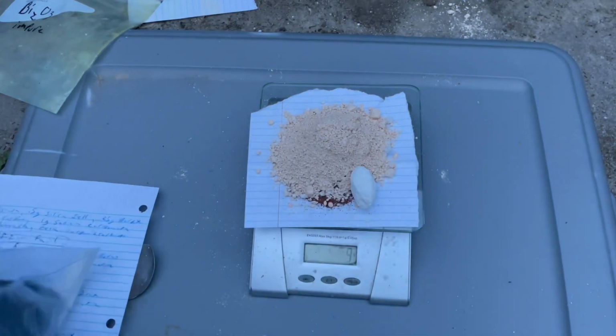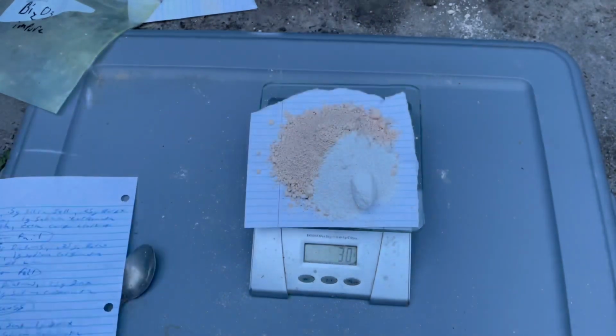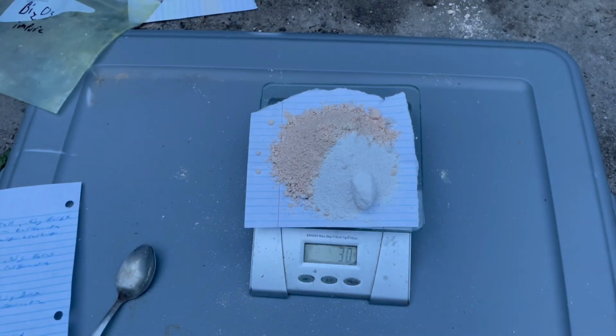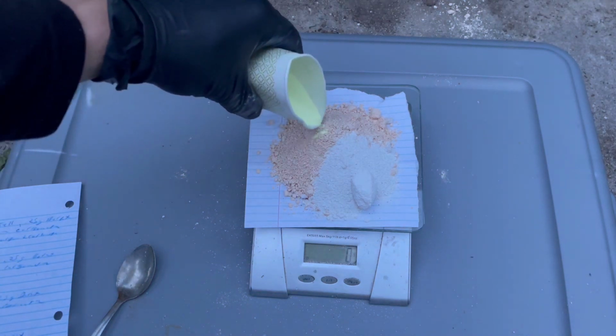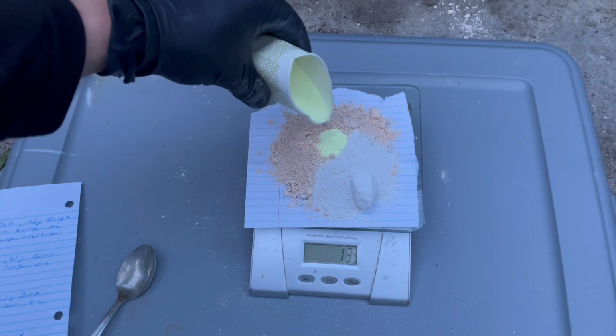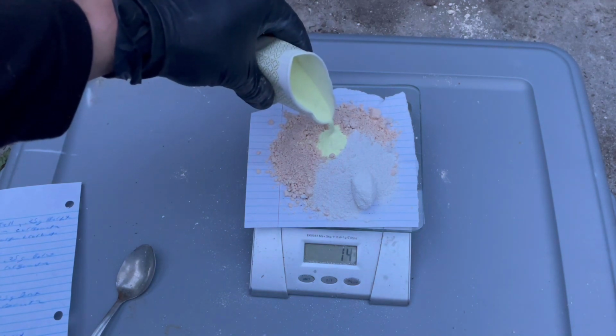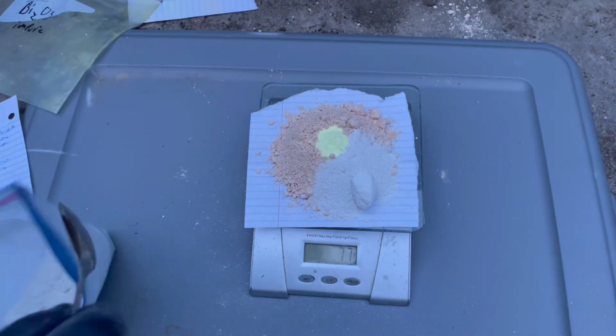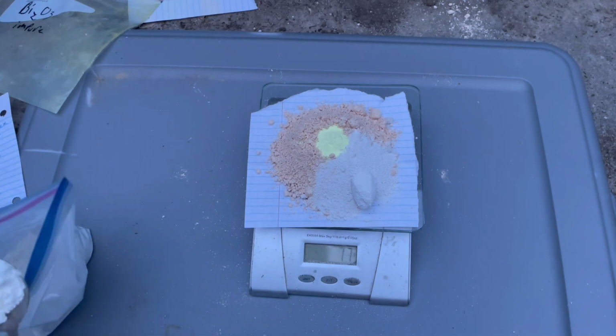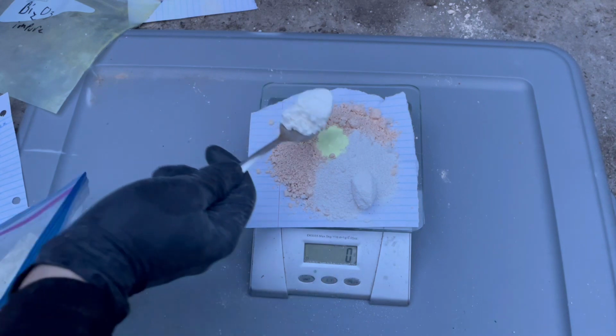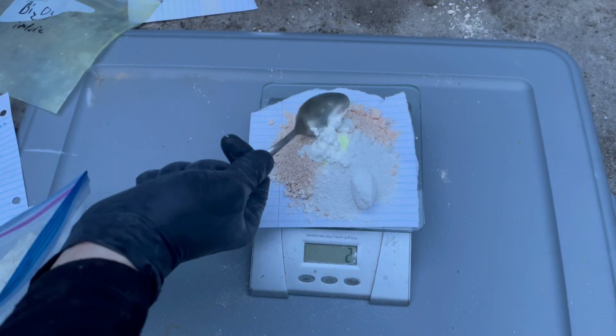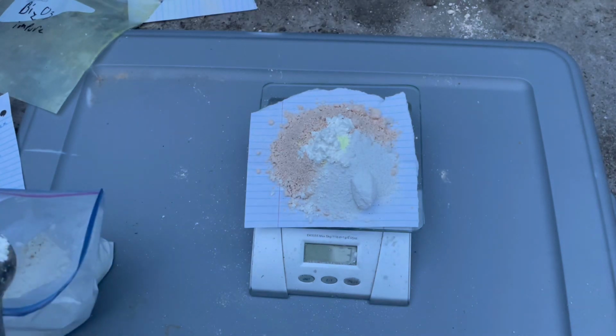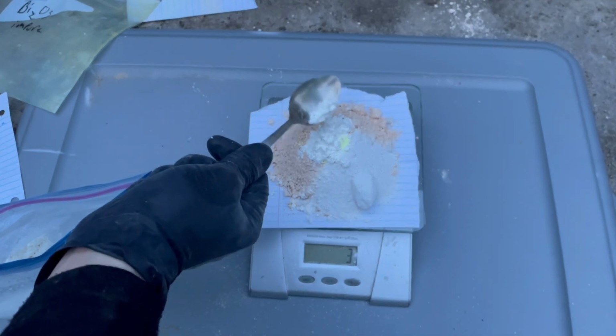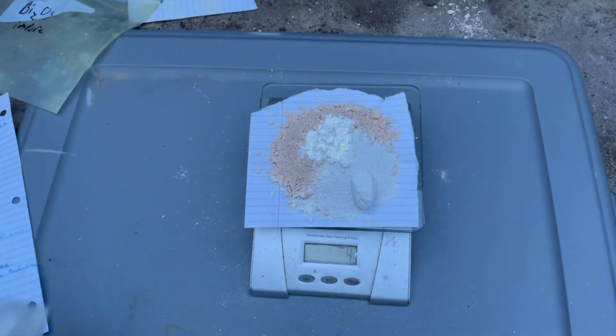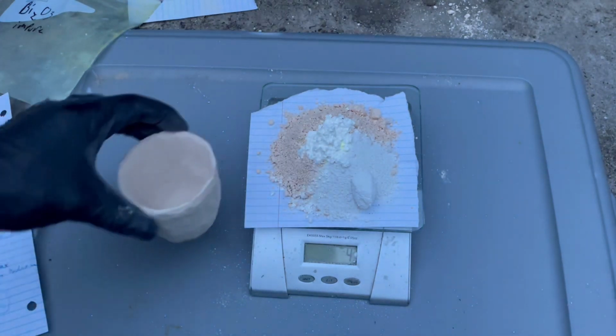30 grams of sodium carbonate. Okay. 16 grams of bismuth oxide, just like before. What was it, 17 grams. Now, for my testing, I discovered that I needed more starch. More than the 2 grams. So I'm going to go up to 3 or maybe even 4 to counteract the iron oxidizing it. There we are. Okay, get that mixed up and put it in a crucible. Hopefully it's big enough.